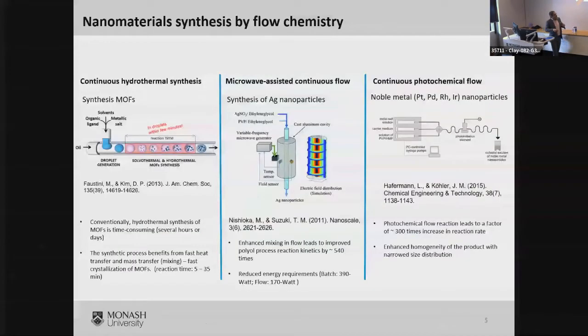Now, some examples. Nanomaterial synthesis by flow chemistry. This is a work published in JACS, MOFs. We have a pretty big group here at Monash working on MOFs. And typically, when you're synthesizing MOFs by hydrothermal, it takes several hours or days, okay? Now, this work showed that if you're able to do the synthesis in a flow reactor, you can do this in about 5 to 35 minutes. Very, very fast reactions. Quite useful, actually, to scale up.